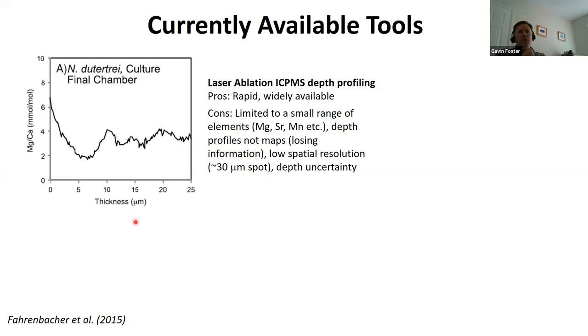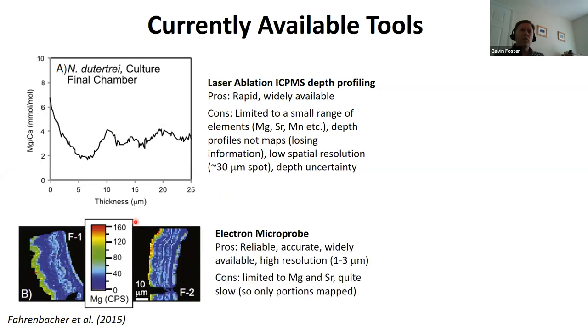Another way of doing this is using an electron probe. This is an electron probe image of the magnesium content. You can see that this section of the shell looks very much like the ablated profile: high on the outside, with this band of middling enrichment. Electron probes are quite widely available. They're reliable, and they can be accurate and high resolution, but they're also limited in the elements you can apply, magnesium and strontium typically, and they tend to be quite slow.